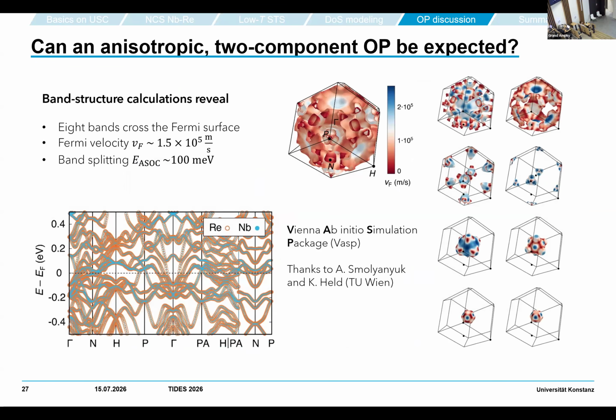So now, can we explain this based on the band structure of the system? For that, we teamed up with Carsten Held's group from Wien and his postdoc A. Smolyanyuk, who used this Vienna ab initio simulation program to calculate the band structure. As you see, it's heavily complicated—we have a total of 8 bands crossing the Fermi energy. Luckily, 2 of them are by far the dominating ones, and the others have smaller contributions.